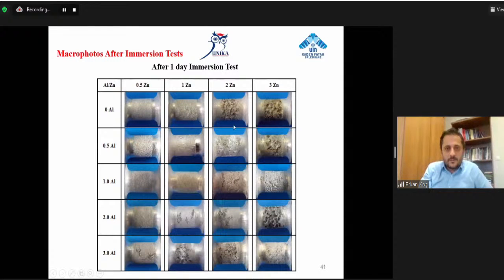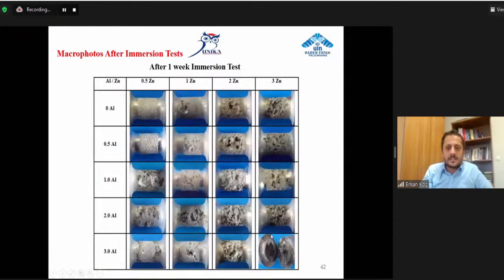After 1 day immersion test, after 1 week immersion test, you can see here, if you use 3 weight% aluminum and 3 weight% zinc, you can lose your samples after 1 week. It means you cannot use 3 weight% aluminum and 3 weight% zinc with magnesium in the body long after 1 week. Okay.